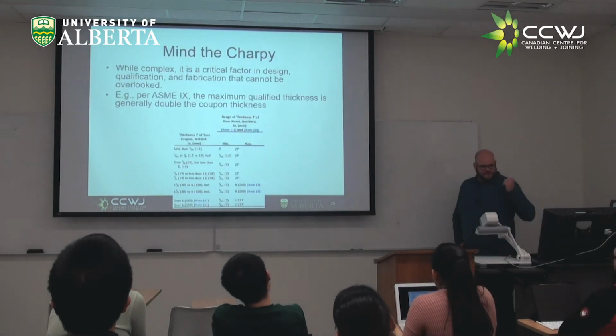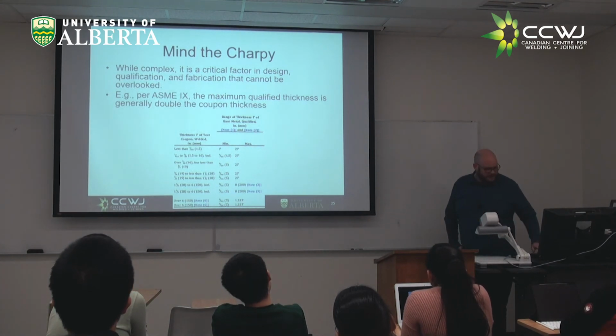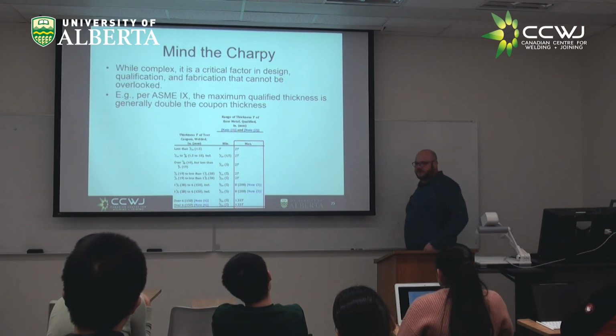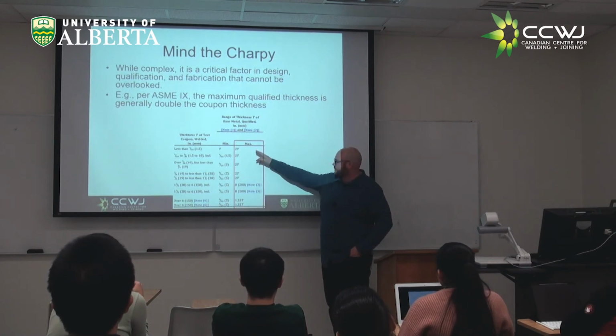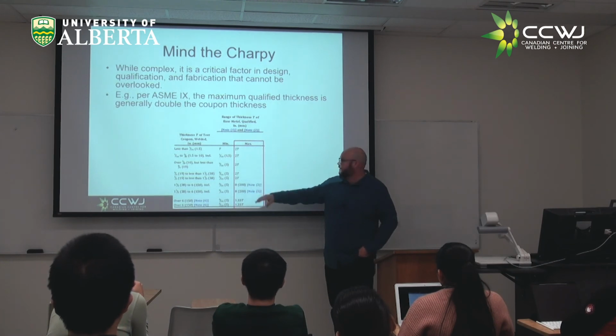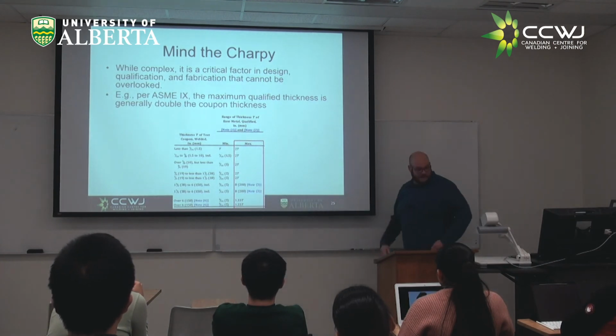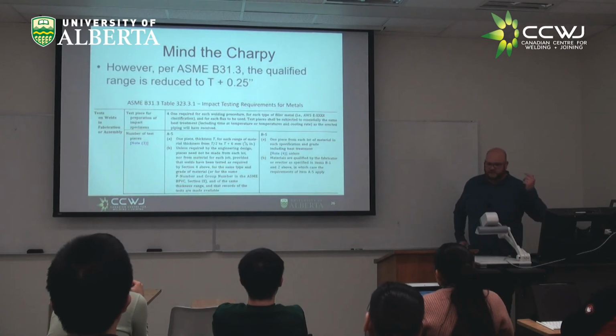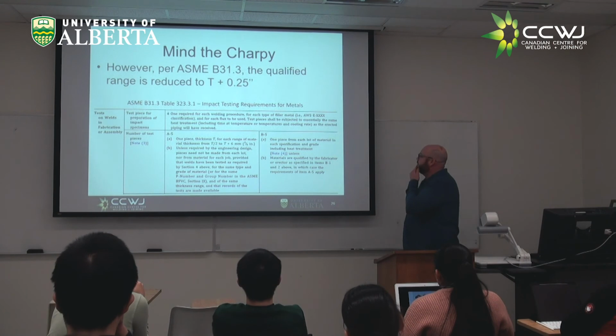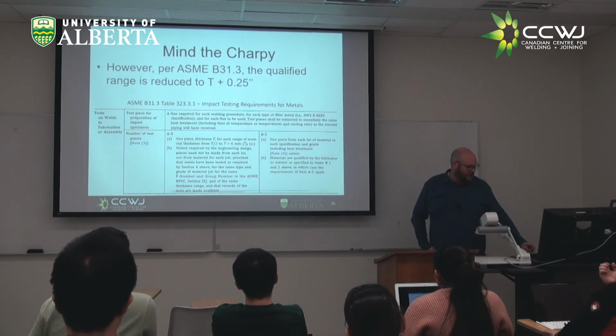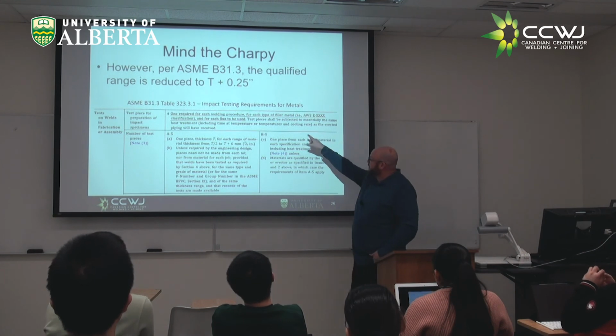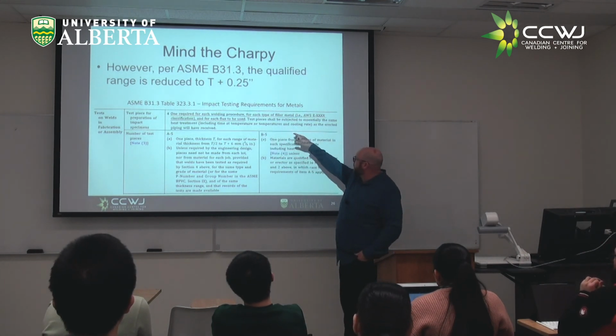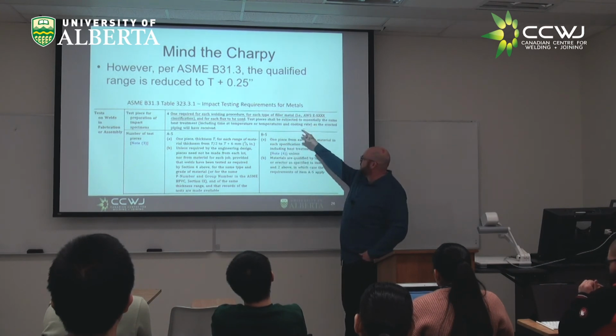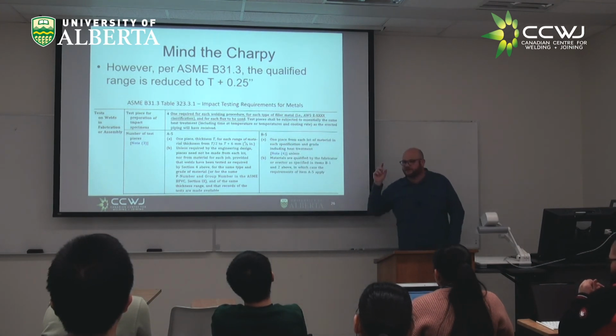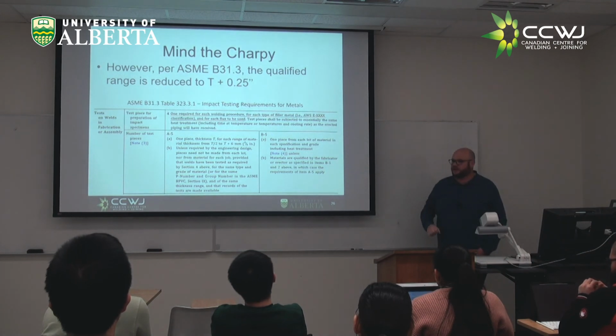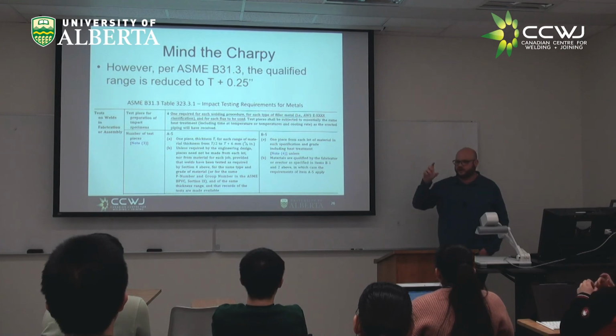So, for example, we talked about beforehand that the maximum qualified thickness for ASME 9 is generally 2T. This applies for supplementary essential variables unless it's something like short-circuiting MIG. So it's 2T for happy days, but then we have to understand the code of construction, because in B31.3 we can see two things. If you require impact toughness, there's also really stringent testing, so you have to do one impact specimen, or one set of 3 Charpys, for each type of filler metal and each flux, and that has its own defined range of qualified variables. So now you're restricting each process that you're using within a larger coupon.